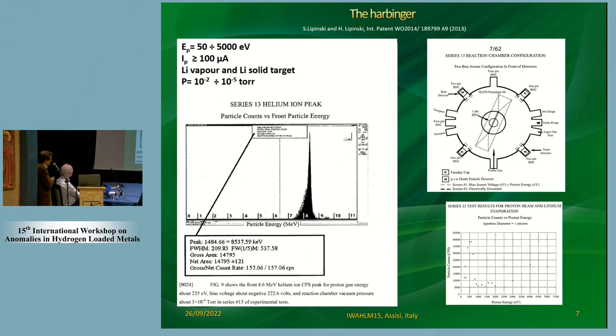The problem is that they tried to apply for a patent, which was rejected because the theory behind this phenomenon was completely crazy. They imagined some sort of gravitational change of the mass-energy ratio. It's a very complicated thing that was also published, but has found no evidence anywhere else. So, in general, when you apply for a patent, you should also have a valid background theory, not only some experimental evidence. And I think this can be a comment on what we said this morning about the need for a valid theoretical model.